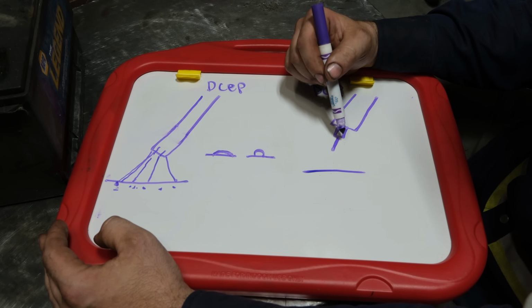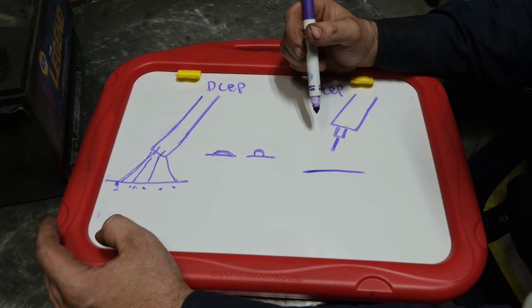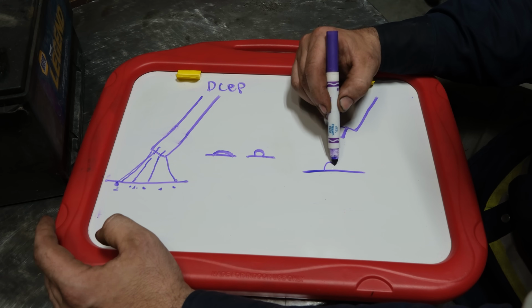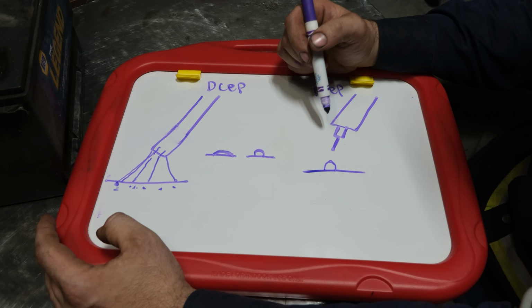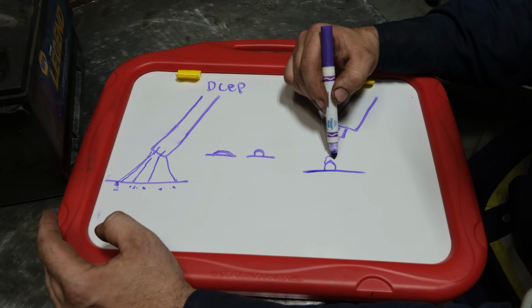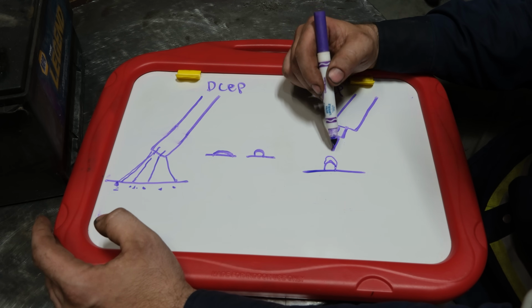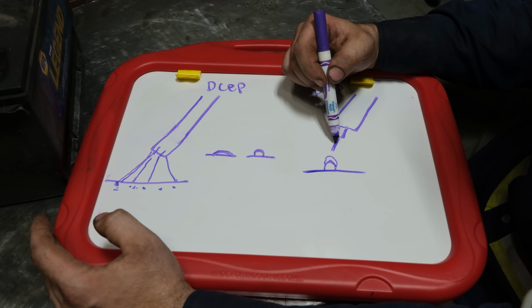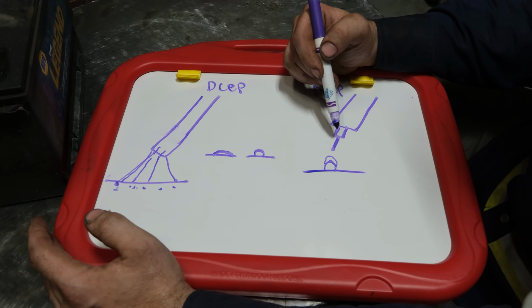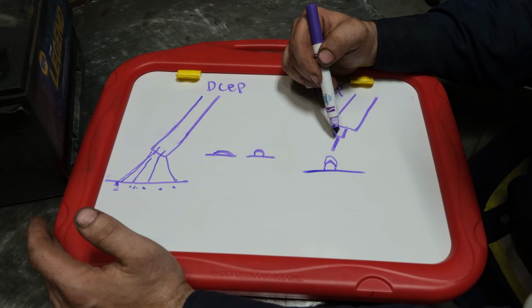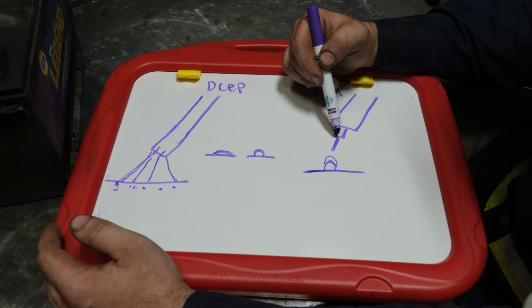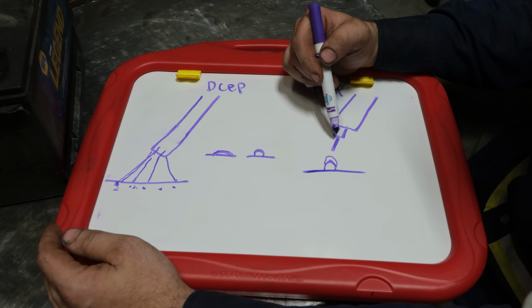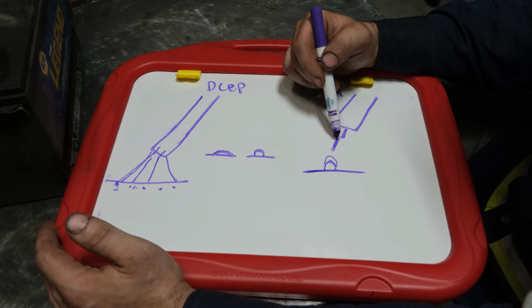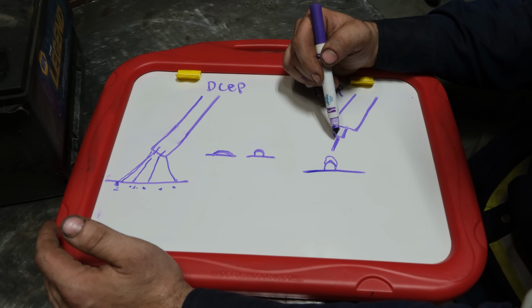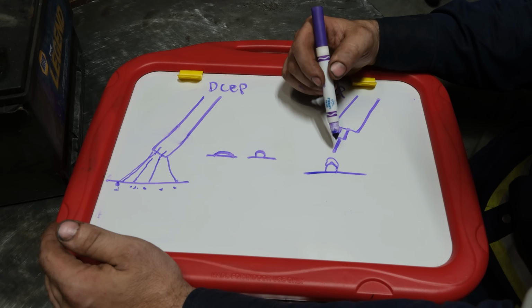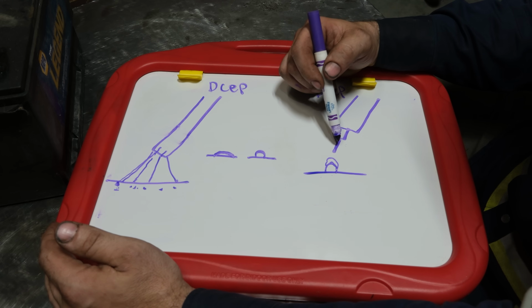If you were to weld MIG DCEN, what would end up happening is your weld would more or less just rope completely up, and no matter what your settings, it would just basically keep putting more and more metal higher and higher, and it wouldn't wet out. And a lot of that has to do with the fact that with MIG, you don't run a very big rod, your .035, .030 wire, but you're running very high wire feed speed. And that's the difference, is that you're substituting diameter for volume, and you still deposit very big welds, much like with stick, you're just feeding a lot more wire.